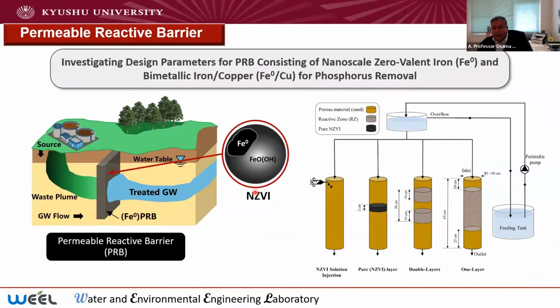We also apply the concept of the nanoparticles to recover or remove the phosphorus as a nutrient from the water, and we simulate the situation of the permeable reactive barrier, which is a kind of barrier that can be constructed to treat the groundwater from the contaminants. So in this case, we apply several scenarios to introduce the nanoparticle into the permeable barriers.